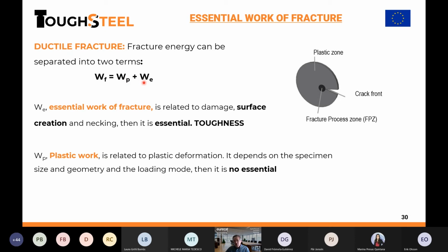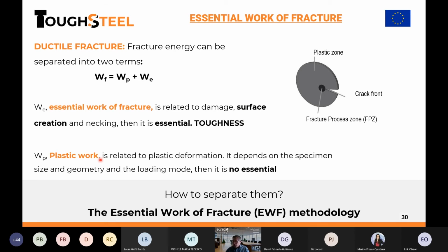This is surface creation and necking. This is essential. This is what the material itself, the microstructure, does. This is why we call it toughness. And the surrounding plastic work is plastic deformation. It depends on the specimen geometry, size and the loading mode, and it's not essential. It depends from specimen to specimen. So the point is that in a fracture test, we have to be able to separate both terms. This is not easy, unless you use the essential work of fracture methodology.